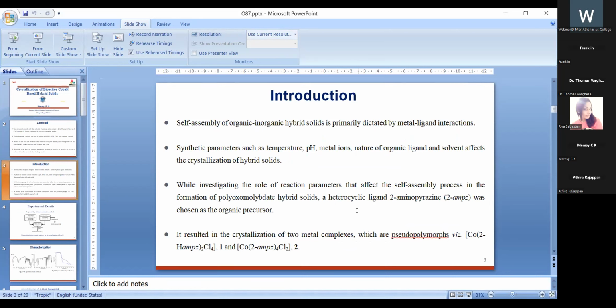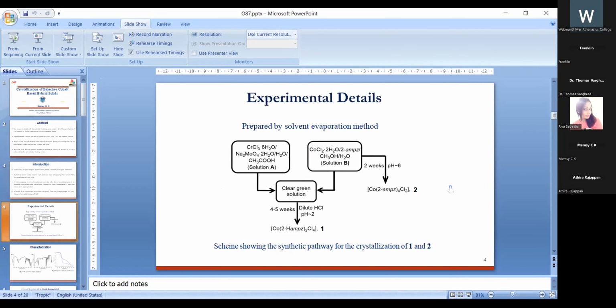While investigating the role of reaction parameters that affect the self-assembly process in the formation of polyoxomolybdate hybrid solids, we selected a heterocyclic ligand, 2-aminopyrazine, as the organic precursor. However, it resulted in the crystallization of 2 metal complexes, which are pseudopolymorphs. Solids 1 and 2 were prepared by the solvent evaporation method as per the scheme shown here.